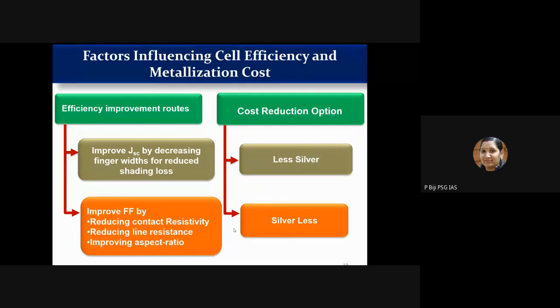Then considering the cost, how can you reduce it? You have to either replace silver screen printing. If you are reducing silver screen printing, then the cell performance is affected and the other technologies are not so matured. So you can also think of a less silver process. You can reduce the consumption of the silver by adopting many methods which can be used to reduce the silver usage. What you have to do is alternative metallization. Alternative metallization means you have to use comparable metallization without compromising the conductivity, but at the same time the cost of the metal should be very low. So obviously we will look towards copper only.